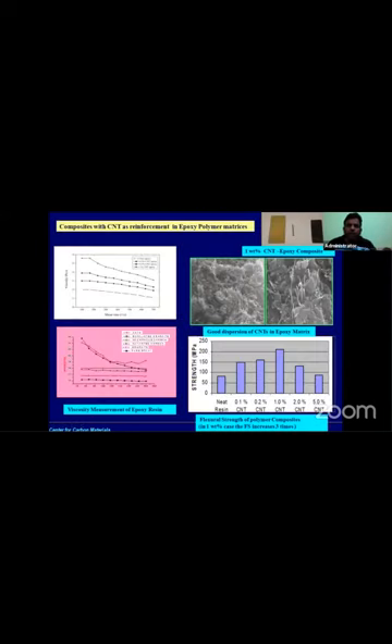In composite applications, an epoxy polymer is completely yellow, but by adding a very low percentage, just 1 weight percent, of CNT, since the surface area is so high, it has become completely black. The strength of the pure polymer is about 54 MPa, or 60 to 70 MPa, and it has become almost 200 MPa just by adding 1% CNT. So properties can be enhanced in a big way.